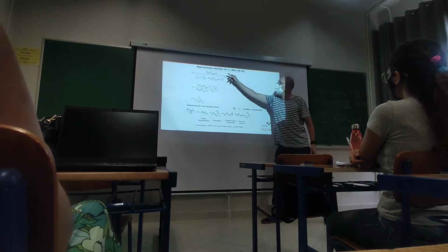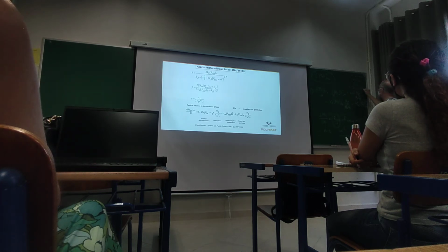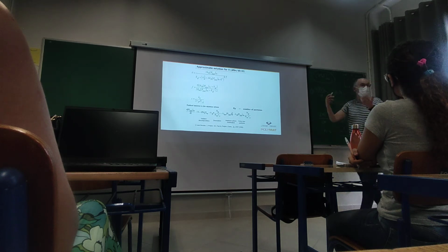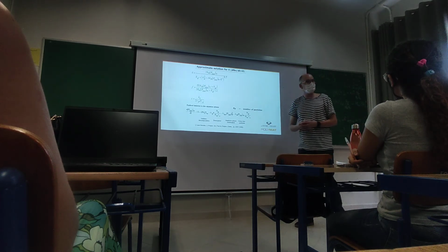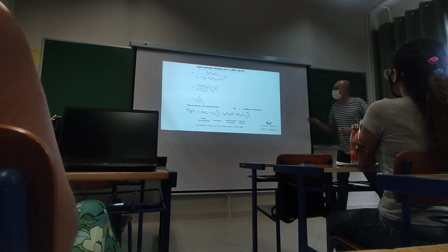As a third step, with the P dot, you go now to this equation, you calculate N bar, in the fourth step, so this is calculated. Now you compare if N bar calculated and N bar assumed are equal. If they are equal, you are a genius, if you do it for the first time. But if not, you come back, and in a few iterations, you will get the two solutions, N bar and the radical concentration in the aqueous phase. Okay? So this is a way.